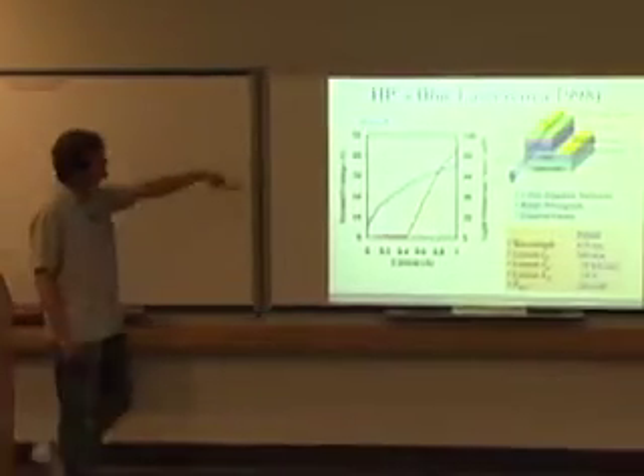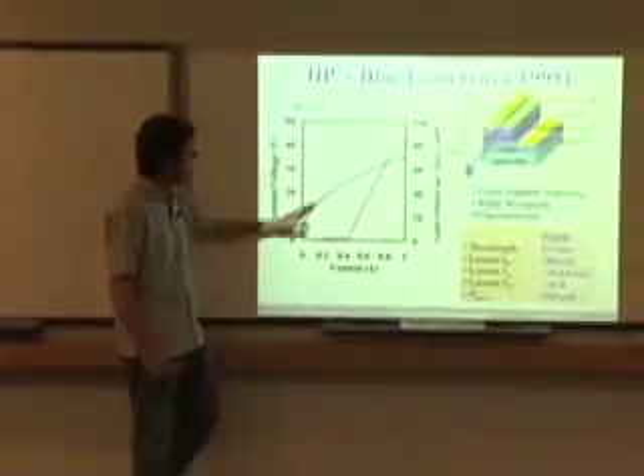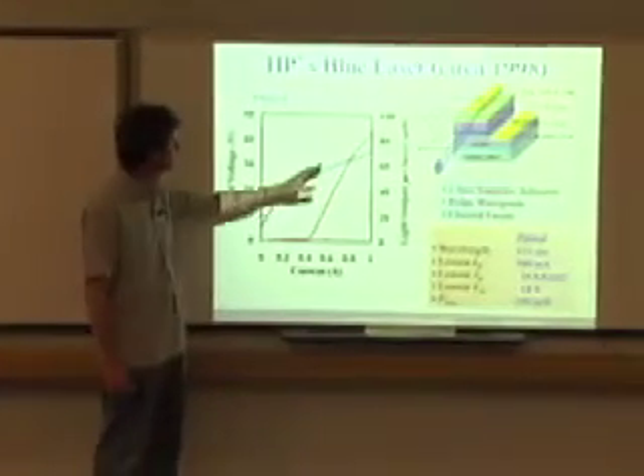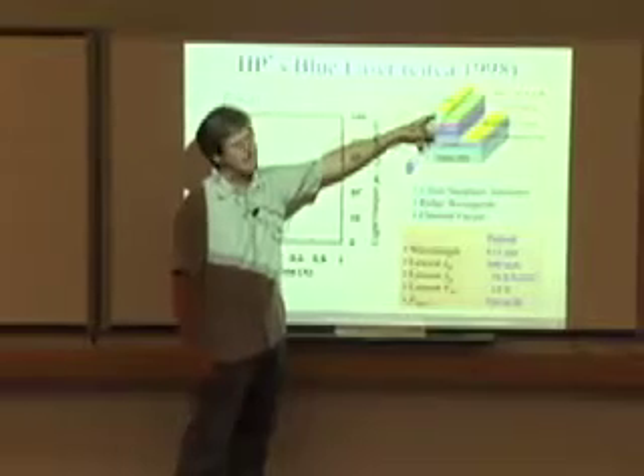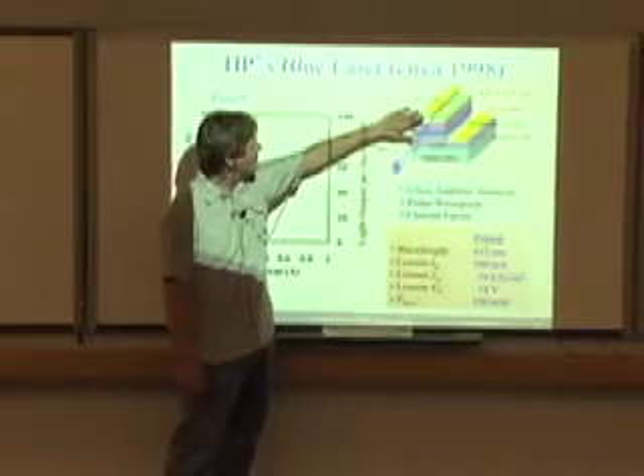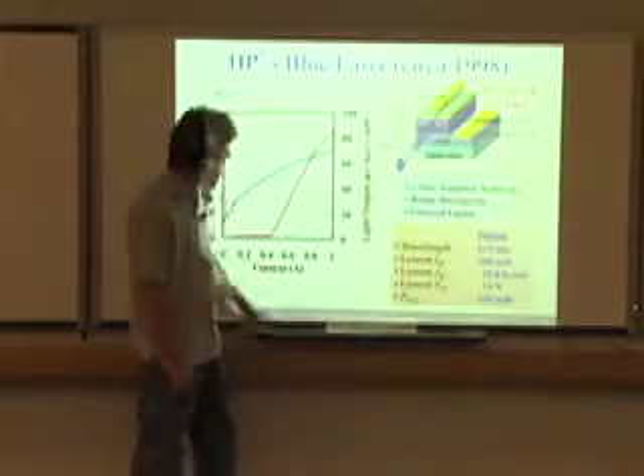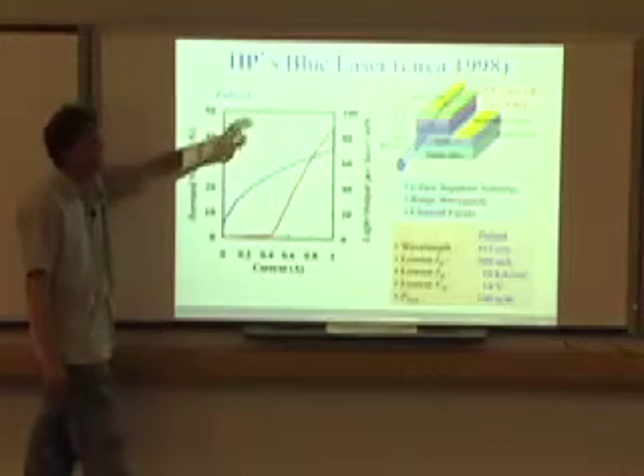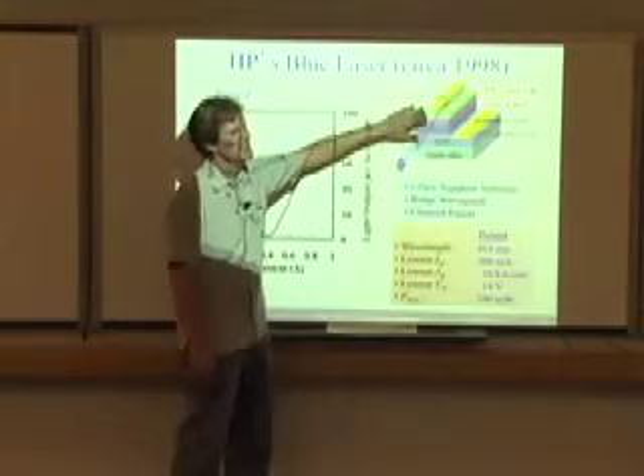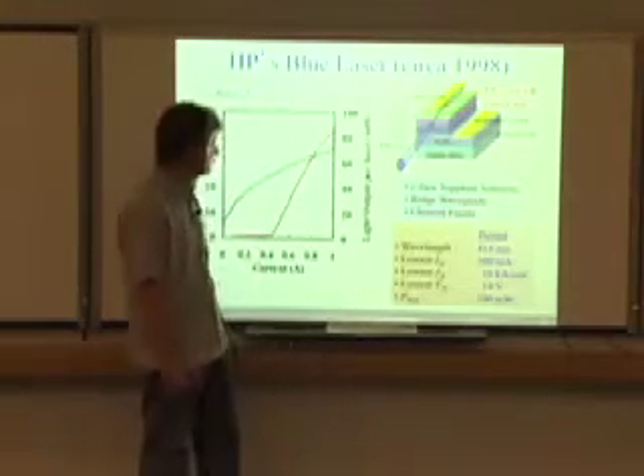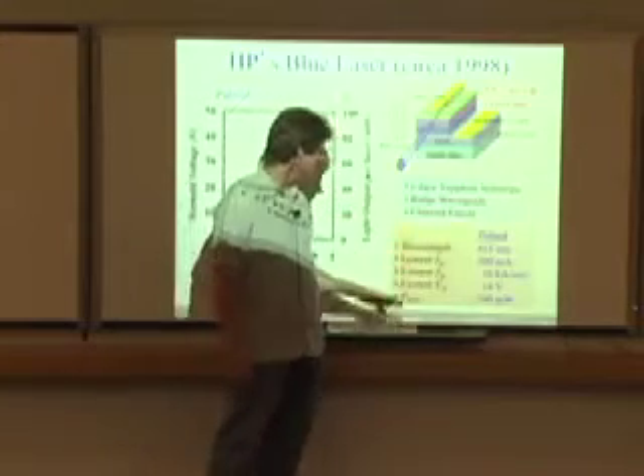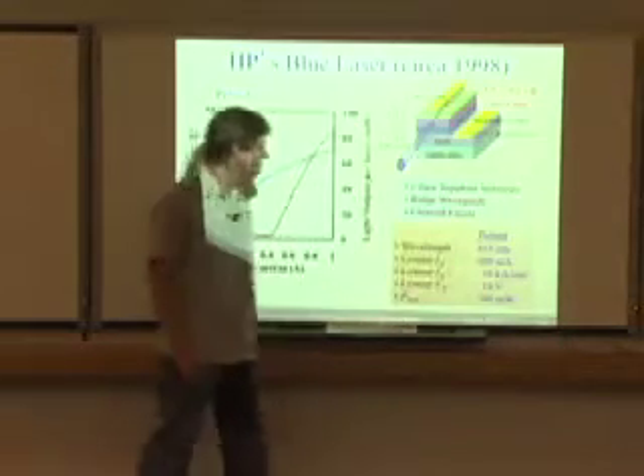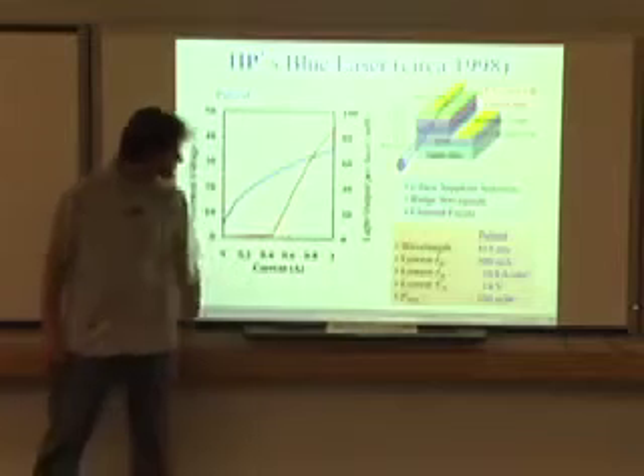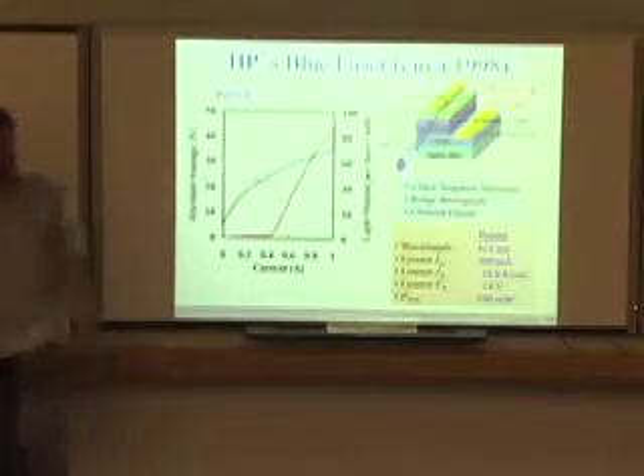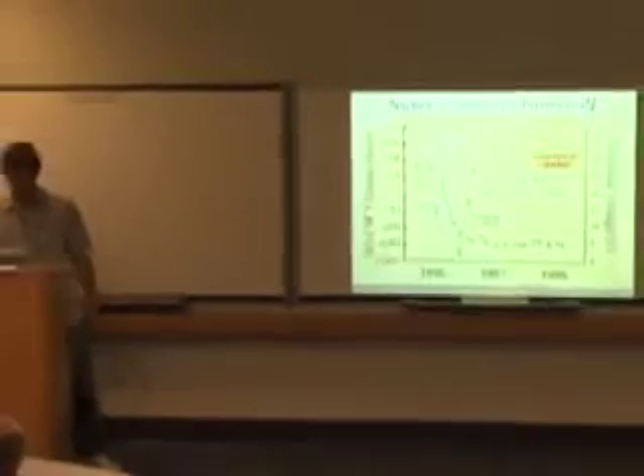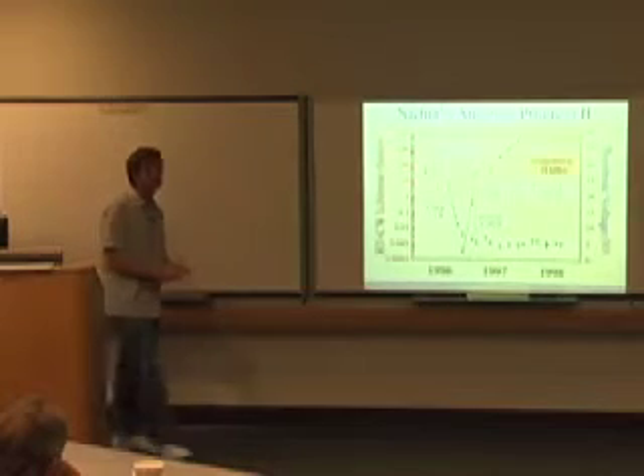And HP, we were in the same situation. We had pretty bad IV characteristics. We couldn't figure out how to get good contact resistance and good low resistance through that AlGaN layer. And we just didn't know what Nichia was doing to get such good IVs. Thresholds, we got down to about 300 milliamps. Threshold voltages, 14 volts. Output powers in the 100 milliwatt range, pretty comparable to what other people were doing. So Nichia's amazing progress too.